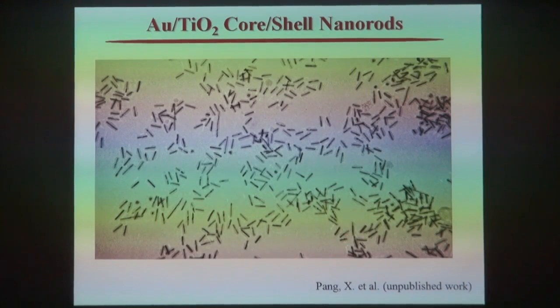So by, again, as I said, rationally designed bottle brush like tri-block copolymer, you can make core-shell nanorods. In this particular case, gold-TiO2, plasmonic semiconducting core-shell nanorod. So here you see the center of the core-shell nanorod appeared dark. That comes from high electron density gold coated with TiO2, a relatively lighter shell. So this is core-shell nanorod.